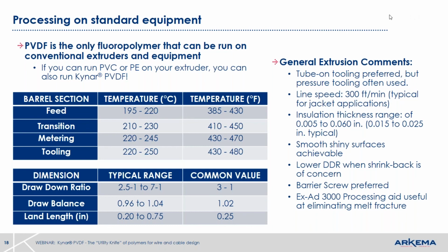In running PVDF jackets in wire and cable, we recommend tube-on extrusion, but you can pressure extrude as well. Typical line speeds are about 300 feet per minute, depending on which grade you choose. Generally, a jacket of 15 to 25 mils is normal, but you can always go thinner or thicker. If you seek a shiny cable jacket, that's achievable. If you want a matte finish, you just have to lower the die temperatures a little bit, and you get a matte finish.